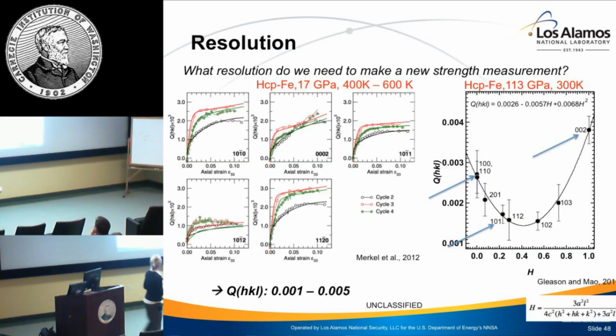So there's this Q factor that was used in the other study, essentially looking at the magnitude of the deviatoric strain, and it's parameterized. This H is just a parameterization of lattice plane. So typically what happens is you measure your different lattice planes, you have your various Qs, your various magnitudes of deviatoric strain, you take some sort of average. But best is to have the end members here, so some value to bound the edges essentially of this parabolic fit, okay?